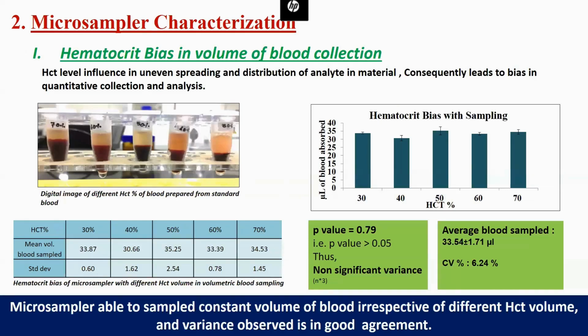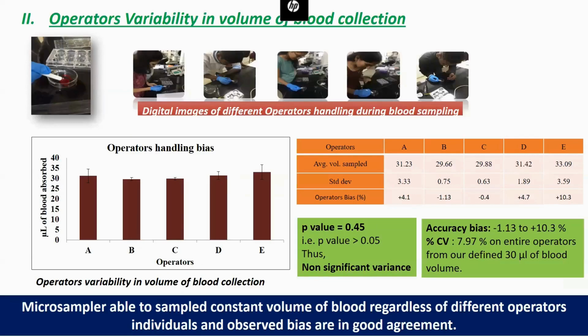Then we tried to understand, if blood is being drawn, how well it can suck the blood irrespective of the hematocrit volume. If the hematocrit volume changes, then the sucking of the blood by the porous matrix through capillary action could be poor. When we checked different hematocrit levels from 30 to 70, we found that the bias was non-significant, and our matrix was able to suck the blood in a better way. Then we also tried to understand, if a person has to self-sample, how much variability there is from person to person. So we took 5 test persons who could draw the blood with our device, and we found that the microliter of blood absorbed didn't change with the different operators using our device.